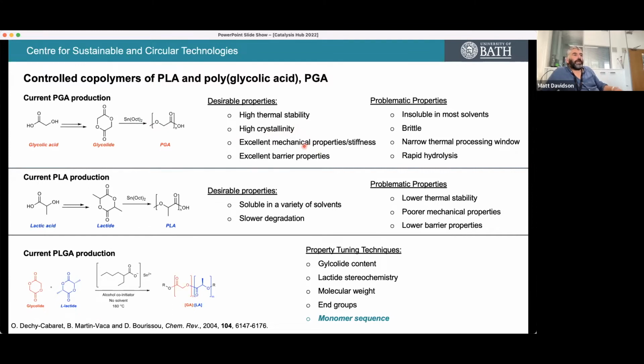So it has really interesting mechanical properties and stiffness, and actually it's used in oil drilling. That's one of the few applications that it's really useful for at the moment. But in fact, it also has excellent barrier properties, so it can be used in a multi-layer film. It has very good oxygen barrier properties, potentially for lightweight packaging materials. But of course, you can't use it as a homopolymer for these reasons.